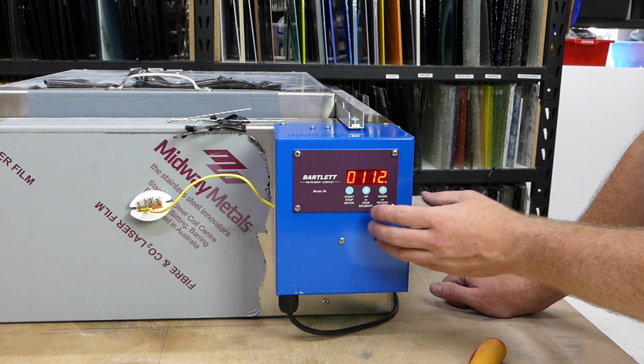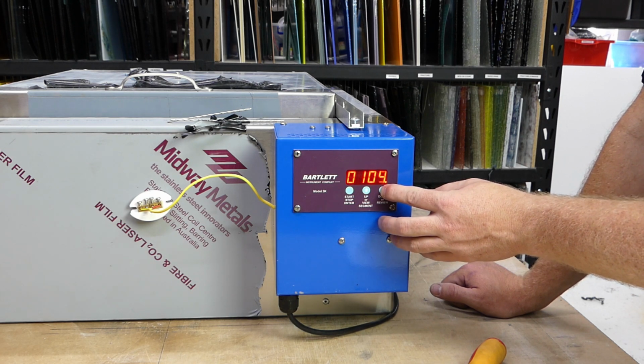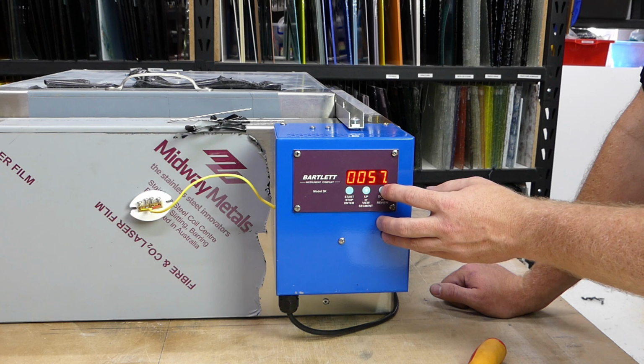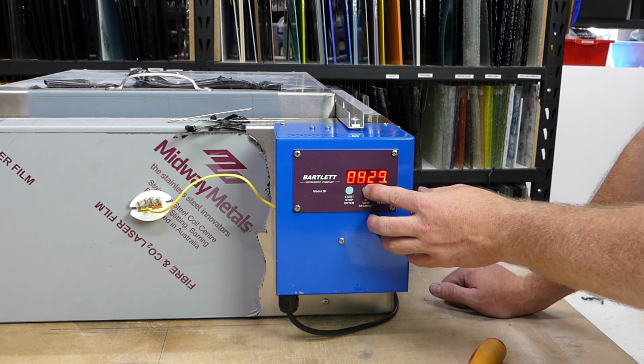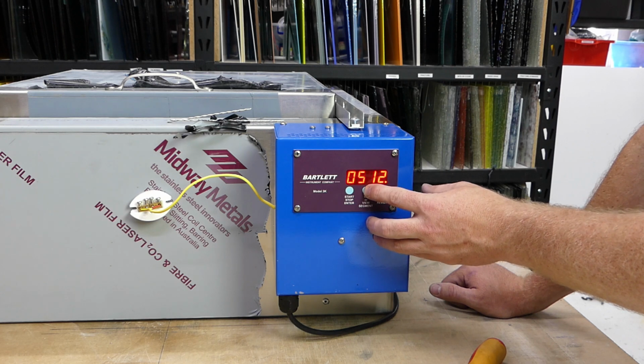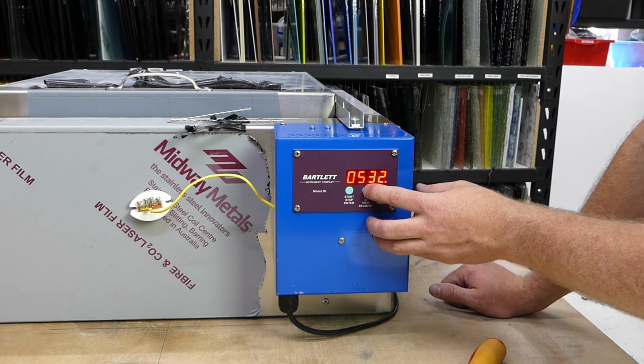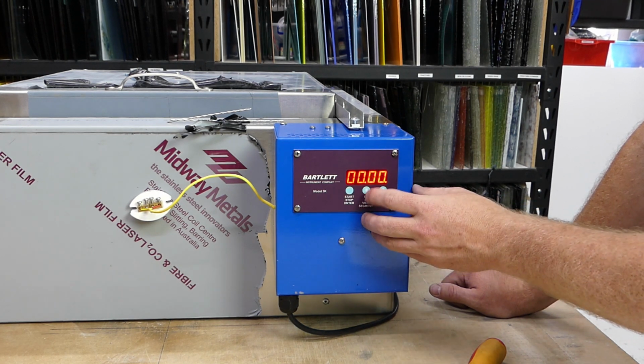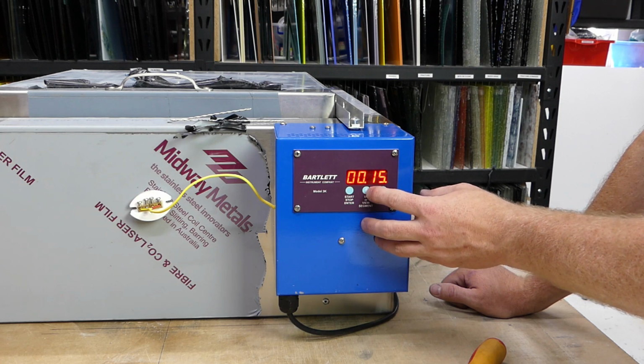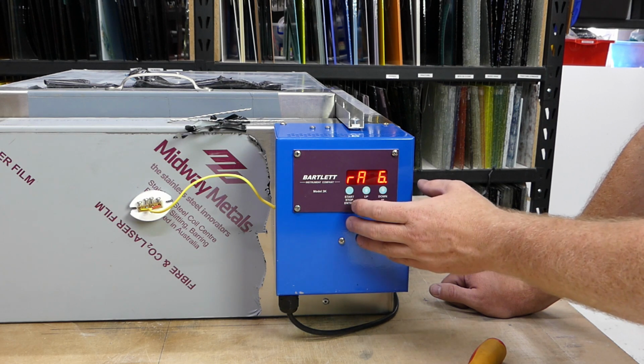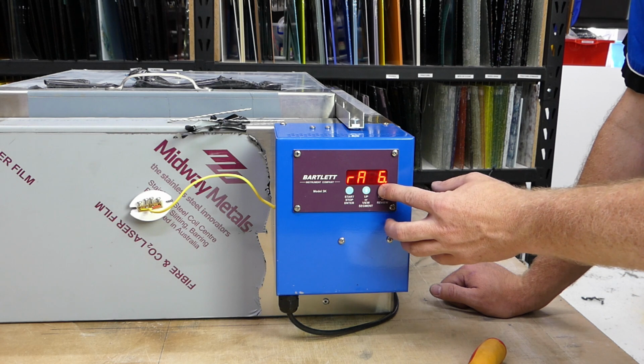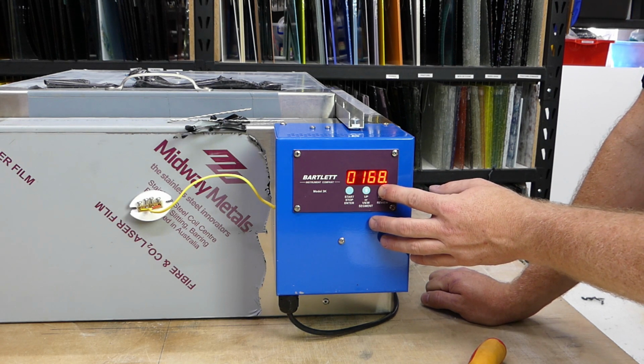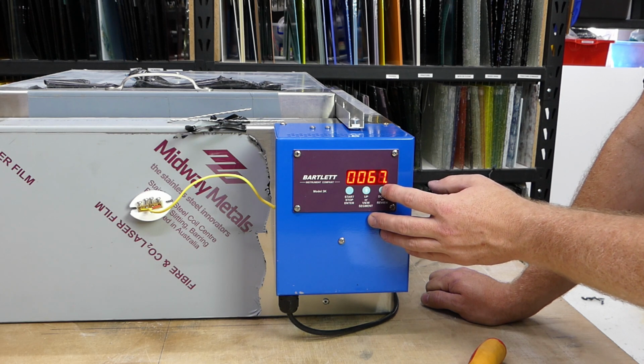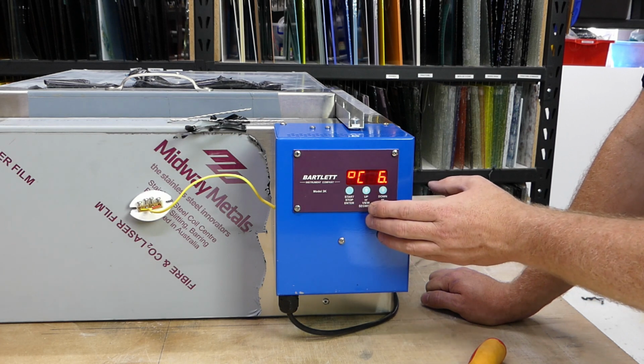Our next ramp is at 60 degrees an hour. And we're going to go down to 538 degrees. And we're going to hold that for 20 minutes. Our next ramp is at 60 degrees an hour again. And we're going to go down to 516 degrees and hold for 30 minutes.